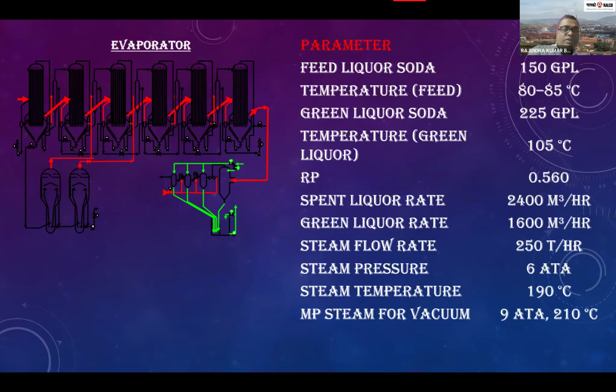Evaporator. Here we are using the feed liquor soda 150 GPL. Temperature of feed is 80 to 85. Green liquor soda is 225. Temperature of green liquor is 105 and the RP is 0.560. Spent liquor rate is 2400 meter per hour. Green liquor rate is 1600 meter per hour.